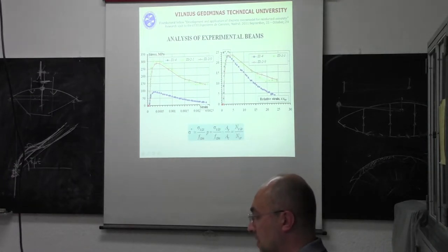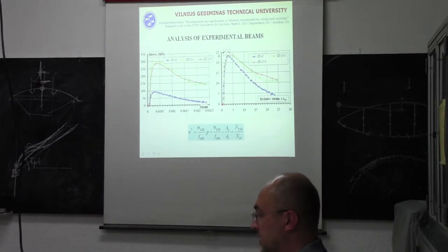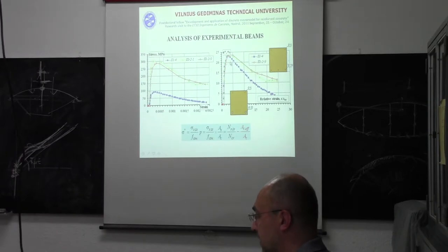this value does not reach 25%. And practically it was the same for all beams. If we assume that this is something equivalent to the ratio of effective area of concrete to whole concrete area, we can think about